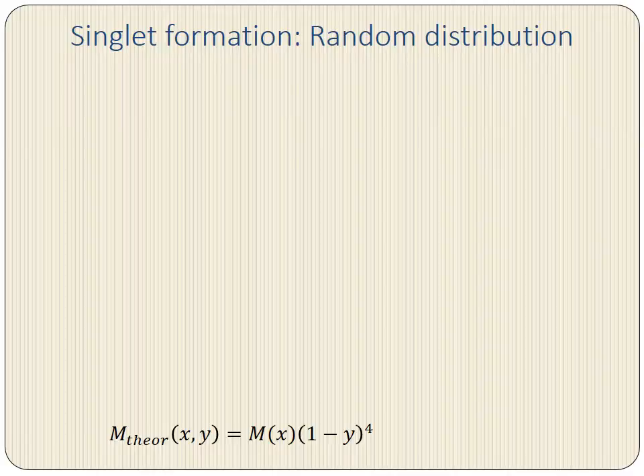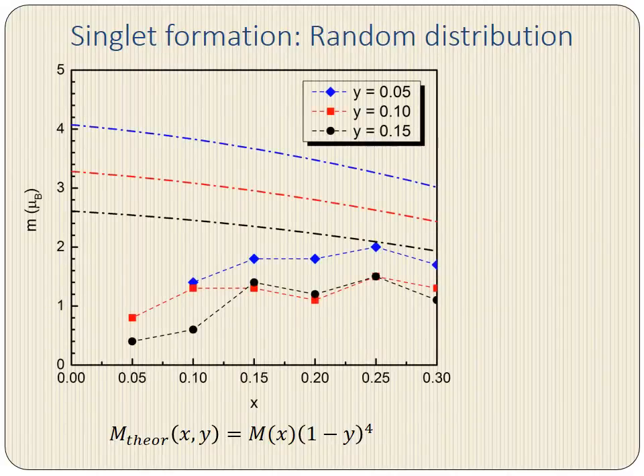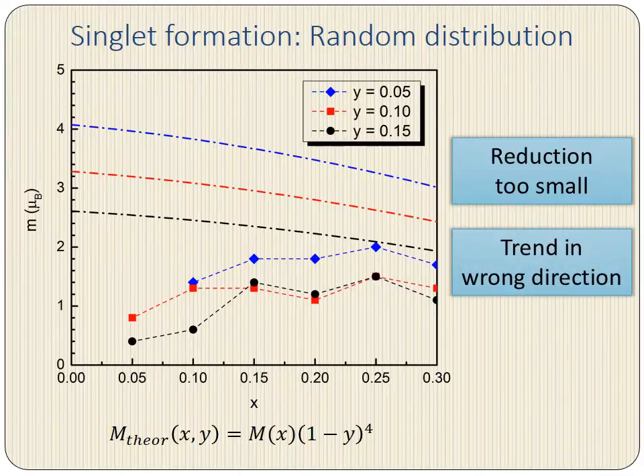We fit to the magnetic moments in our calculations to obtain m of x, and then we compare our results with experiment, which we see in the plot. We do see that we get a reduction, so this is at least somewhat promising, but overall the agreement is not good. In particular, there are 2 problems. One, the reduction is just too small, and worse, the trend that we see is in the wrong direction. Notably, our results are decreasing with increasing hole doping, whereas experiment moves in the opposite direction. Something else must be at play here.